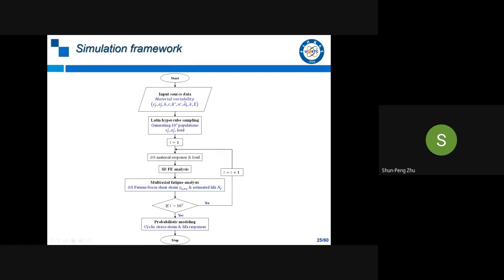And here is a flow chart for this simulation. Actually, from the input sources, we take the variability from these parameters. Using Latin hypercube sampling, we generate 1,000 populations with loads for each cycle. And for each cycle, with the one input material response and the load, we run 3D finite element analysis and output the FS, the Fatemi-Socie shear strain, and also the estimated life, and then output the stress-strain response and also the life response.